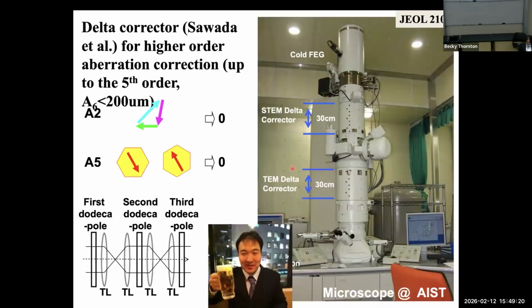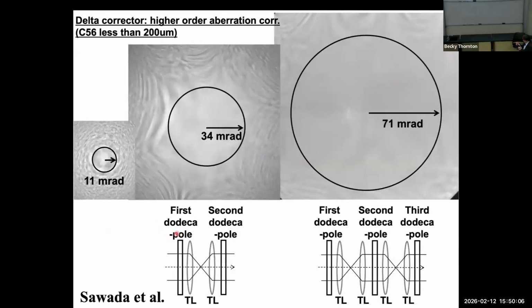We have a very nice guy in Japan, Dr. Sawada. He designed a new corrector to get rid of this 5th order 6-fold aberration. He made 3 dodecapoles, and the 6-fold aberration made by the first and second dodecapoles can be compensated by the 6-fold astigmatism of the second and third dodecapoles. This gives you very nice resolution, even at low acceleration voltage. So this is what we made at the beginning of our project.